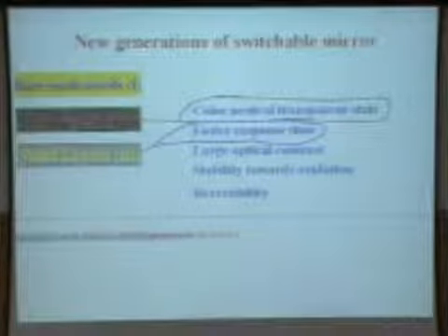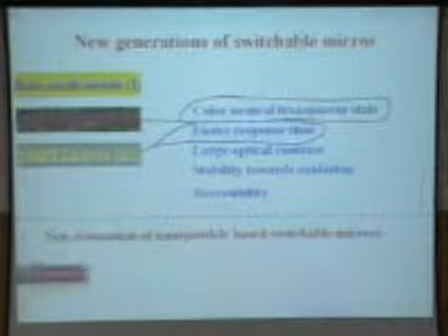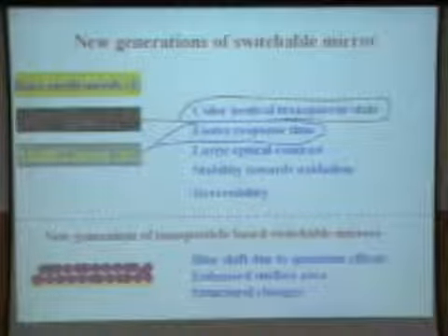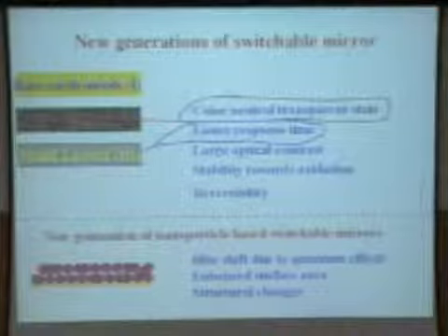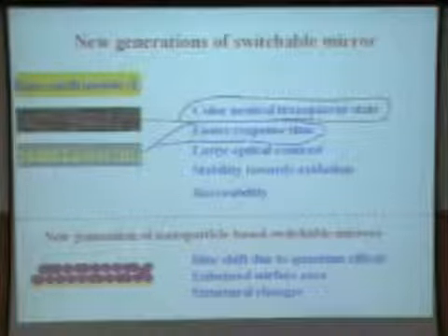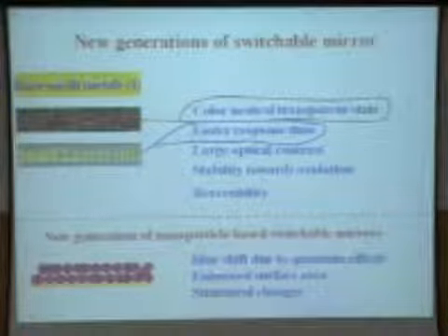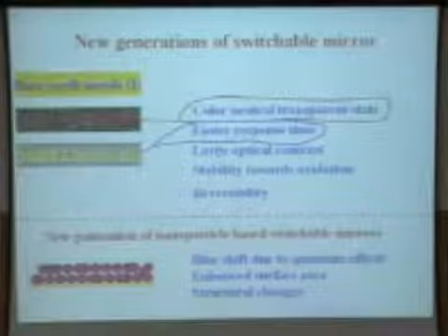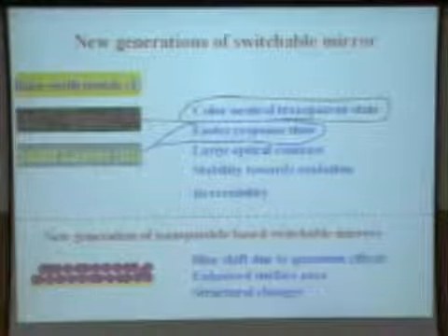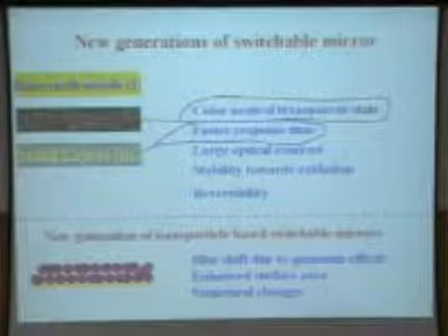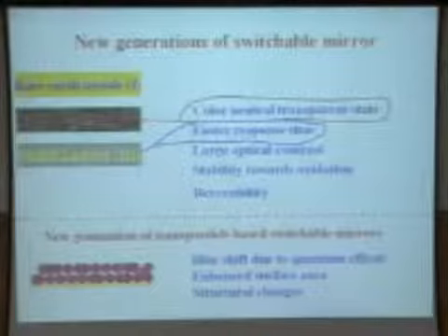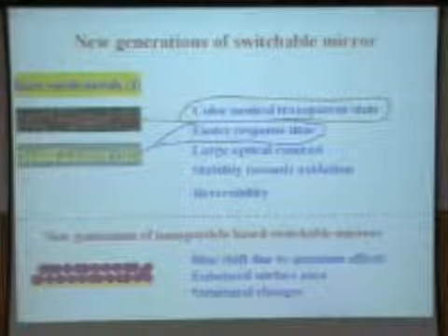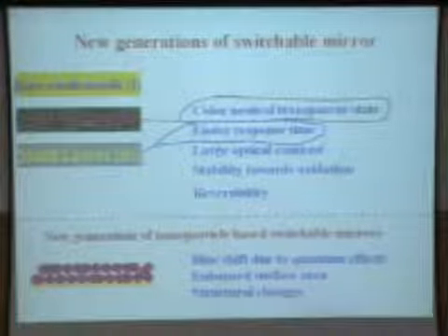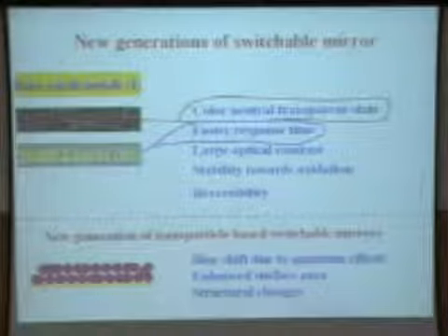Around 3 to 4 years back, we thought of using nanoparticle-based switchable mirrors, rare earth nanoparticles. There were 3 reasons why we thought we should make switchable mirrors based on rare earth nanoparticles. First, blue shift, which all of us know, due to the quantum confinement effect. The trihydride state is a semiconducting state. In a semiconductor, if you have nanoparticles and you confine the electron to a small dimension, there is an increase in the band gap of the semiconductor. And that yellow color was due to the band gap of gadolinium trihydride.